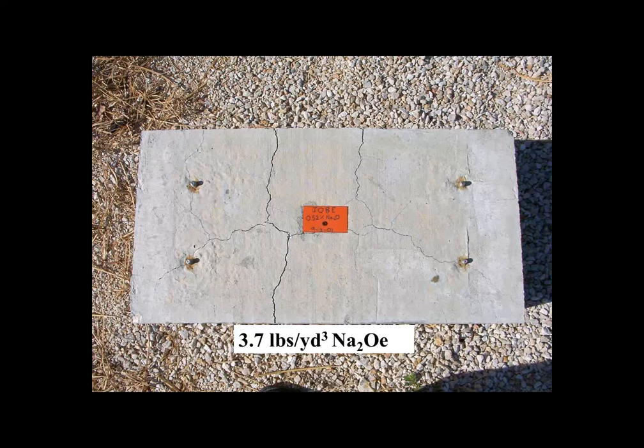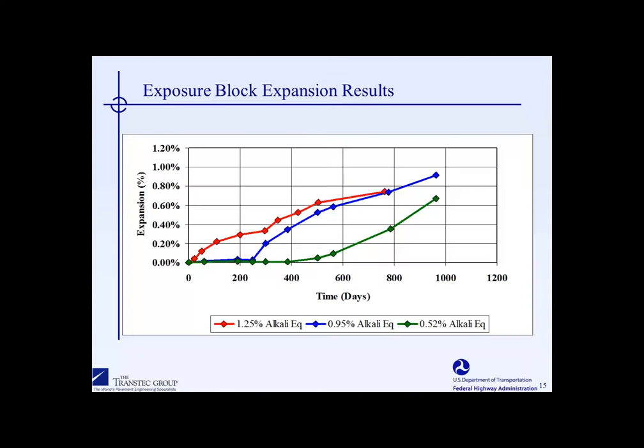The third block I'm going to show next here is the same mix design, but now we've intentionally used a low alkali cement, which is 0.52% Na2O equivalent. And with the same mix design, this gives us an alkali loading of 3.7 pounds per cubic yard, which is actually quite low. But yet, you'll still see that with this highly reactive aggregate we still observe expansion and cracking. It took about a year and a half or so for the cracking to occur, but it certainly does still occur, and it is obvious.